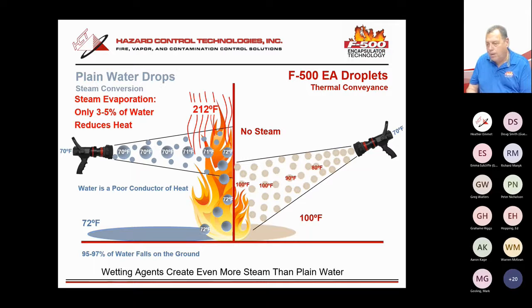And when we talk about thermal runaway and lithium-ion battery, everything that I've seen and read from NFPA, UL, and FM Global says the big problem is thermal runaway, reduction of the heat. We need copious amounts of water to reduce the heat. Here's why. The water is not very effective to reduce the heat compared to the F500. The F500 reduces the heat 10 to 20 times faster than plain water. Let me make sure I'm saying this correctly. The same volume of a 3% solution of F500 will reduce the heat 10 to 20 times faster than the same volume of plain water. And it will do it without creating superheated steam.